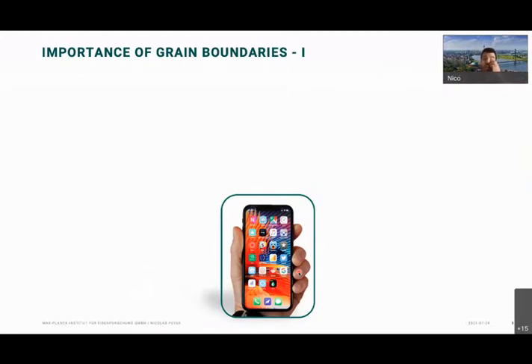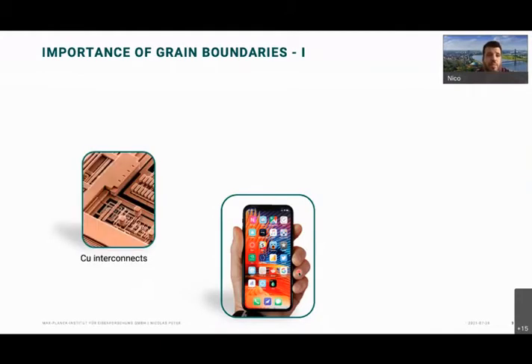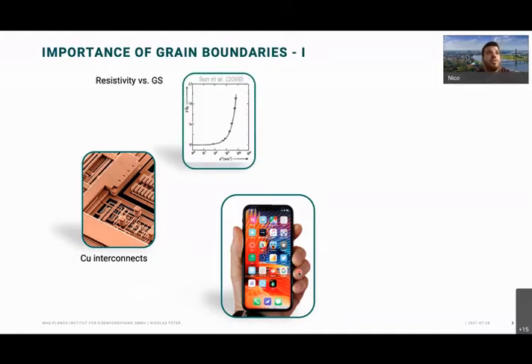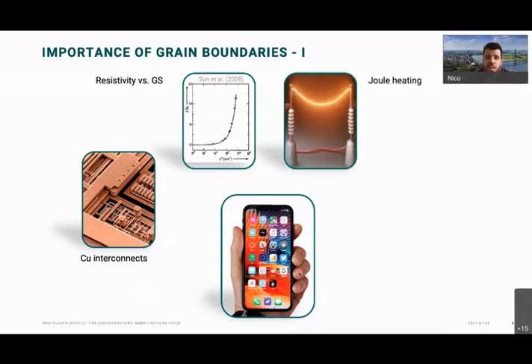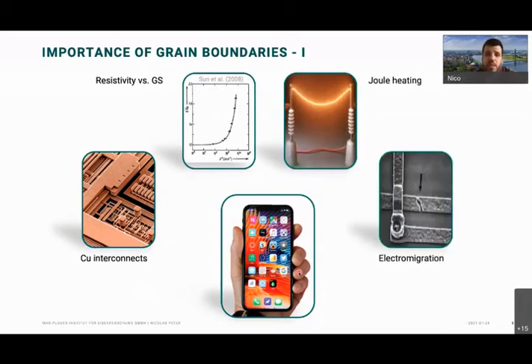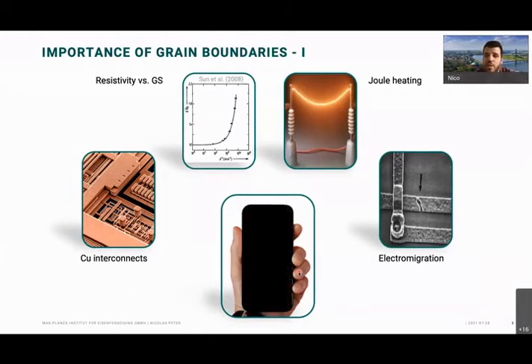So why are grain boundaries actually important? If you take your cell phone, you probably know it has a lot of copper interconnects inside, and they're getting smaller and smaller. And with smaller structures, you probably also get smaller grain sizes. And if you decrease the grain size, some of you might know the resistivity actually goes up. With increased resistivity, you might get pronounced Joule heating, which might lead eventually to electromigration. And this is just a thought experiment, which might then turn off your phone in the end, right?